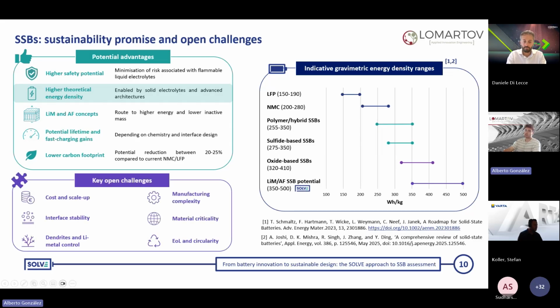Logically, these come along with several potential challenges that also need to be addressed. The first one is the cost and scale up. Current LFPs are already extremely competitive with pack prices that are close to the $100 per kilowatt hour range. In the case of SSBs, the challenge is to manufacture thin solid electrolytes, lithium metal interfaces, and high loading cathodes at an industrial scale and also at a competitive cost.